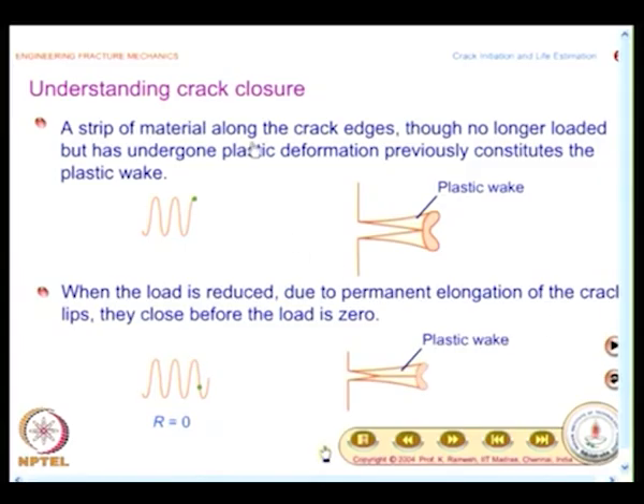a strip of material along the crack edges, though no longer loaded but has undergone plastic deformation previously, constitutes the plastic wake. We had seen it in the previous slide, and what is depicted here is, I have a cyclical loading and I am discussing what happens at this point, that is, after a few cycles at the peak load, the story of the crack would be like this. I would have a crack fully open, but it would have a plastic wake. So, you have the plastic wake shown.